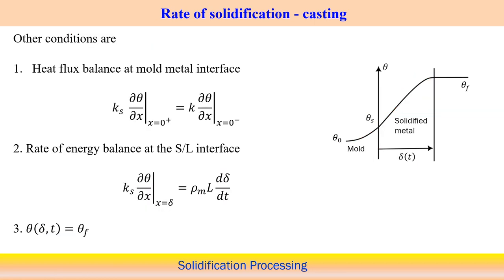Now here along with defining the temperature distribution, we need to define some boundary conditions, because using these boundary conditions we can finally get the complete solution of these two equations. The first boundary condition that prevails here is the heat flux balance at the mold metal interface. So at the mold metal interface the heat flux should be balanced. Definitely what heat is flowing should be balanced. So here we can put the boundary condition like that: Ks del theta by del x at x equal to 0 plus should be equal to K into del theta by del x at x equal to 0 minus.